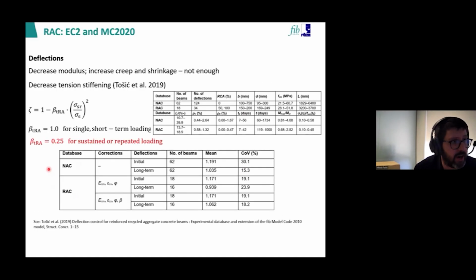In deflections, there are changes, of course, because even if you introduce higher shrinkage, higher creep, lower modulus, you still have an underestimation of deflection. So there is a decrease in tension stiffening. And so this beta coefficient within zeta, which is the interpolation coefficient for curvatures or deflections, for long-term, sustained loading, was reduced from 0.5 to 0.25. Again, this is all empirical fitting on meta-analysis of databases of collected results.